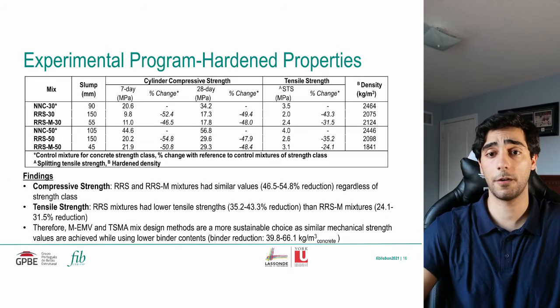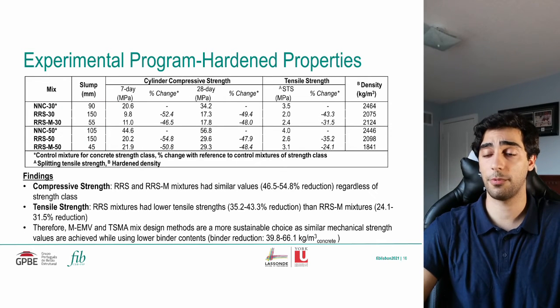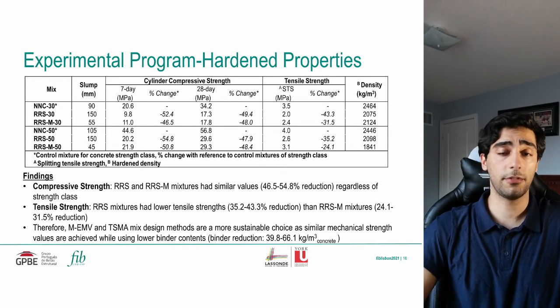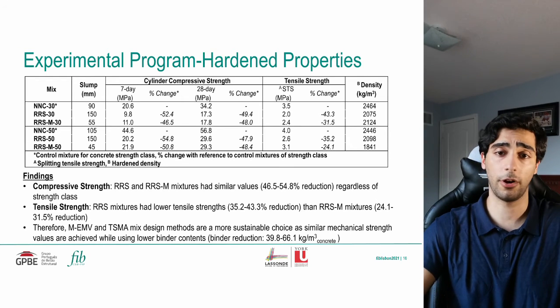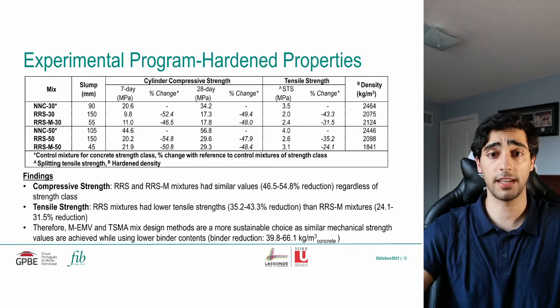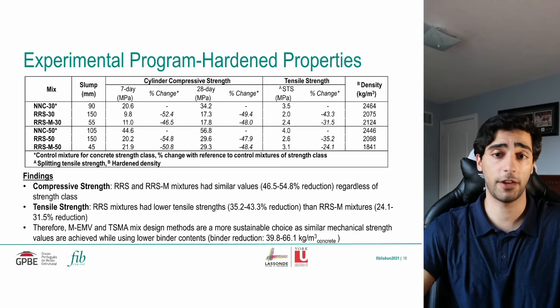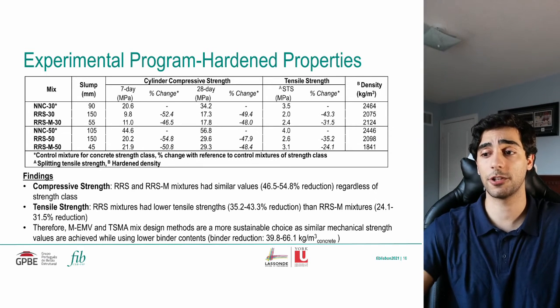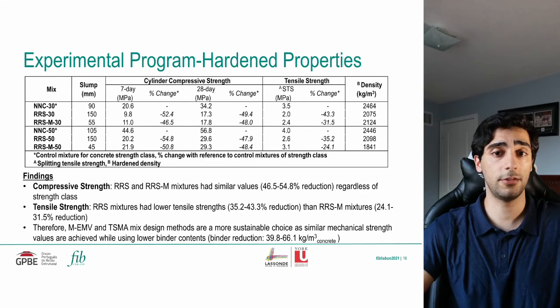In terms of the hardened concrete properties, the values for the various mixtures are provided in the table. In general, it was found that in terms of compressive strength, both the mixtures, regardless of their mixture design method, had similar values, with up to a 54.8% reduction, regardless of the target strength class. In terms of tensile strengths, the mixtures proportioned with the conventional mix design methods displayed reductions up to 43.3% relative to the control mixtures, while the two-stage mixing and EMV-based mix design mixtures only presented reductions up to 31.5%.